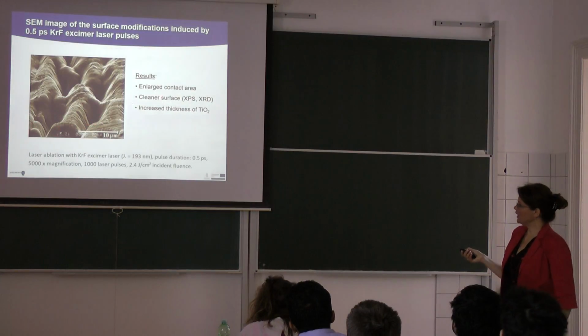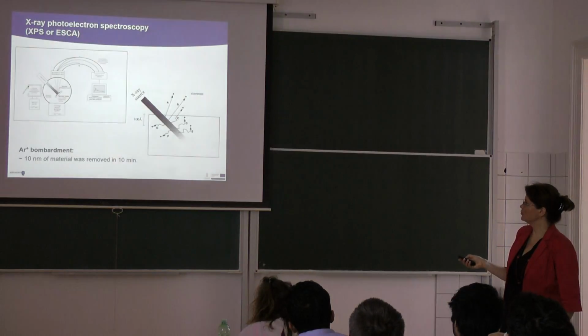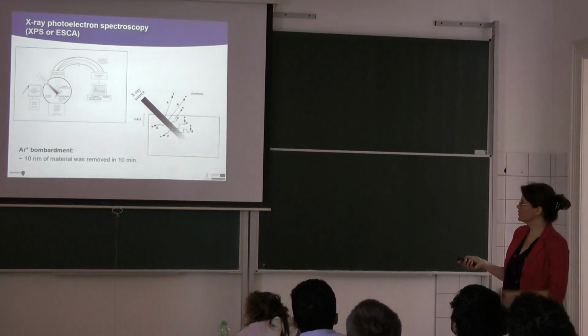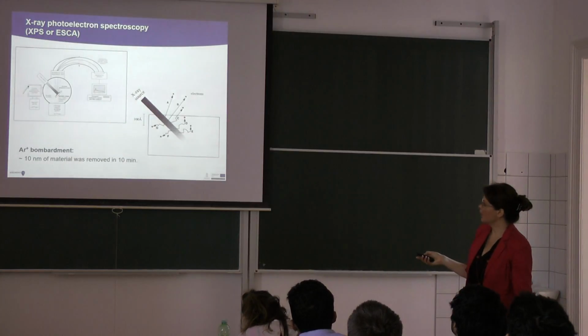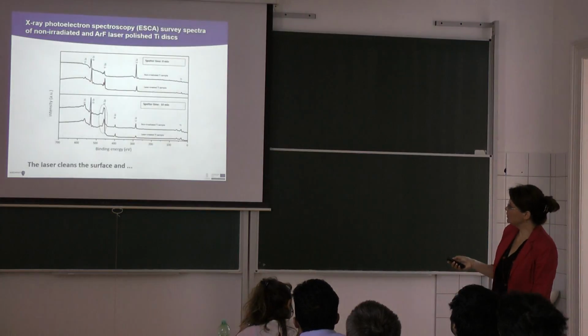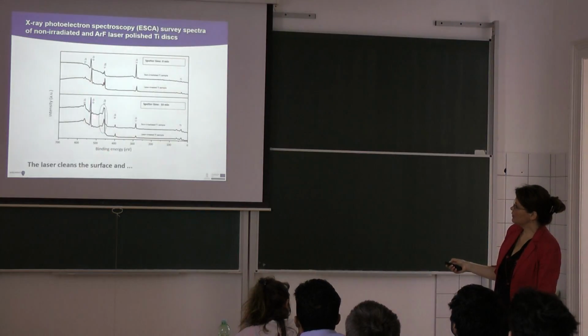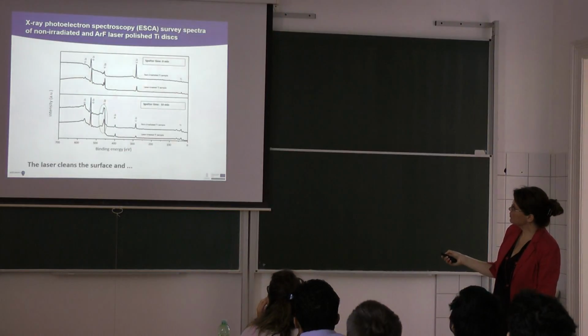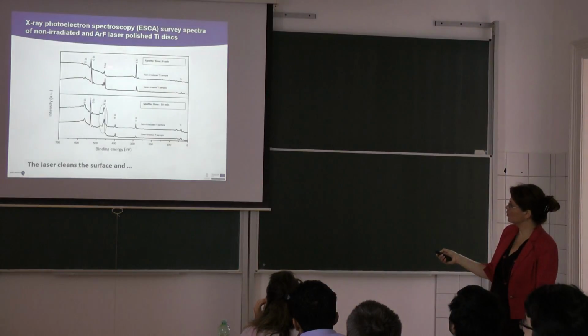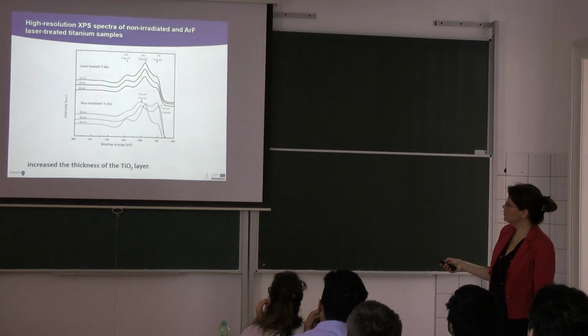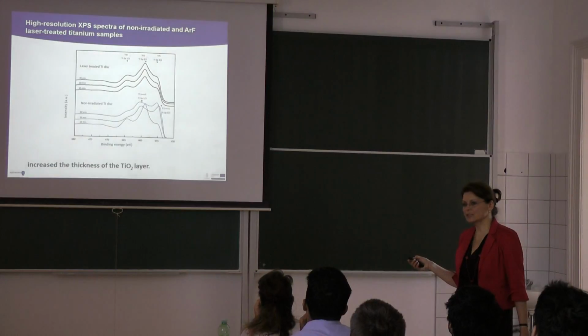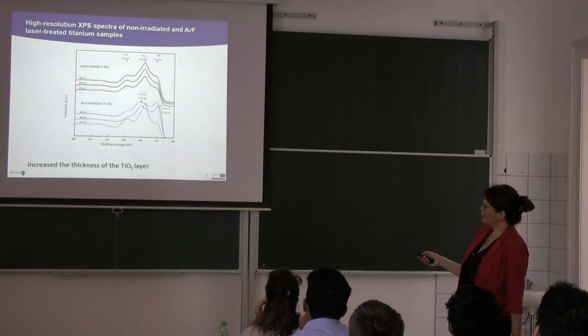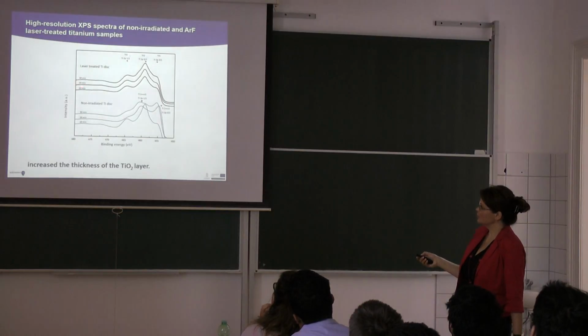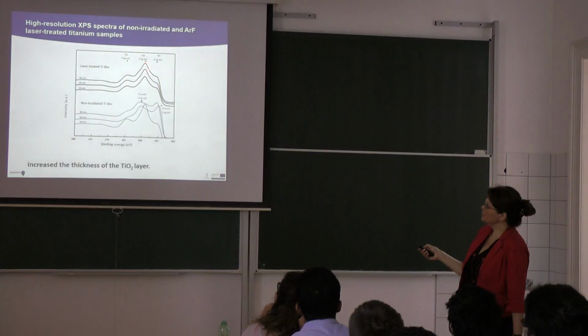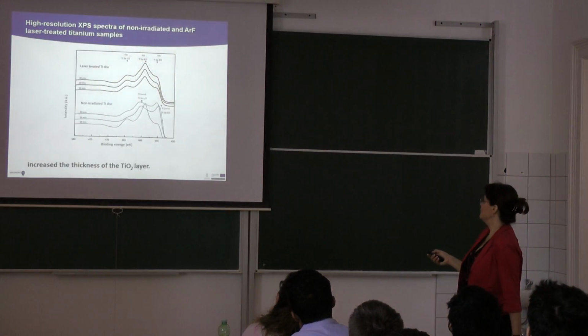And we also showed that we have a cleaner surface and increased thickness of the titanium dioxide. We measured with X-ray photoelectron spectroscopy, and we applied also argon ion beam. I'm sure that you know this system. What we could see here is that the red one is the laser treated titanium sample. This is the control sample. And if you focus on these peaks, you will see very nicely that we could even measure the size of the titanium dioxide layer. And how? Because if you have an argon ion beam for the laser, the peak will be available, which is typical for titanium dioxide.